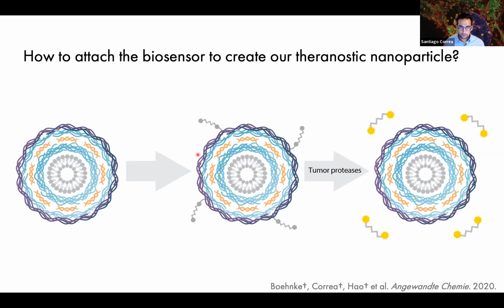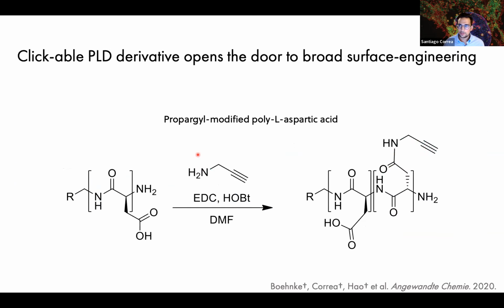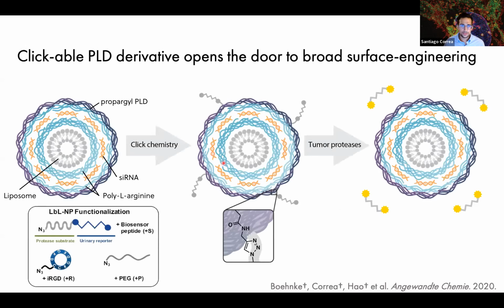And so what we ultimately ended up doing was turning to click chemistry. So we modified around 10% of the carboxyl groups on our polyaspartic acid into propargyl groups, which would be compatible with azide click chemistry. And so using that approach, we now had a way of functionalizing the surface chemistry of these nanoparticles in a way that was really highly flexible. Essentially, any molecule that we could put an azide on, we could incorporate into this nanoparticle now.